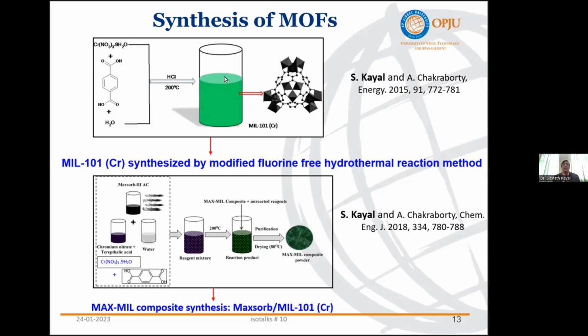And you can see this blue-green colored metal organic framework material we have got. The characteristic feature is that we synthesized it using a green method. Green method means we used only water as a solvent. We didn't use any organic solvent. Also, earlier people used hydrofluoric acid as a catalyst, but we didn't use hydrofluoric acid because it is a very toxic, hazardous chemical and really difficult to handle. So we avoided this hydrofluoric acid.